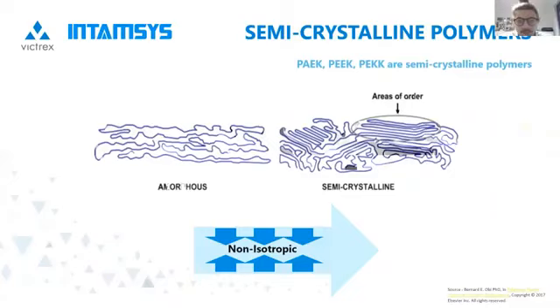So on the right hand side, the PEEK kind of polymers, where they're semi-crystalline, typically are anisotropic in flow, which is shown by the arrow diagram at the bottom. And this means that there's greater shrinkage transverse than with the flow, and the risk of potential dimensional instability, which is why warping and curling can be an issue as each layer is printed. And of course, the latest generation of printers like INTAMSYS Funmat Pro 410 or the 610 HT are pretty sophisticated and seek to provide the right conditions for the demands of these exciting polymers, but they are challenging to print.